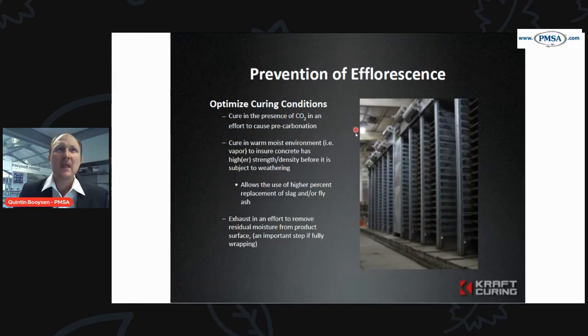So it'll effectively start sealing off your concrete, well, it's not concrete yet, but it'll seal off the surface of the concrete. If you cure in a warm, moist environment, like vapor, the concrete has a higher strength and density before it's subject to weathering. So that will also reduce your secondary efflorescence. Curing also allows for the use of higher percentages of replacements, such as slag or fly ash, because by heating it up, we can get the fly ash to chemically bind with your calcium hydroxide in early stages, and you can get a better or denser concrete quicker.